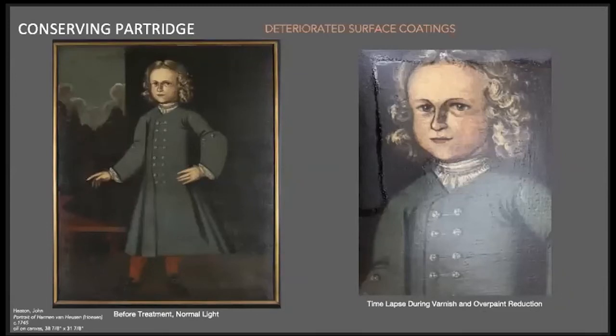The ongoing investigation into the materials and techniques used by Partridge and his contemporaries has helped to understand localized discoloration, fading, and changes in the paint film to inform our approach to treatment. While there is no one treatment path to conserve a painting, the most common initial step for the AHA collection was to aqueously clean the surface of water-soluble dirt and grime, followed by reducing the yellowed varnish and discolored overpaint through the application of free solvents, solvent combinations, and/or solvent gels.